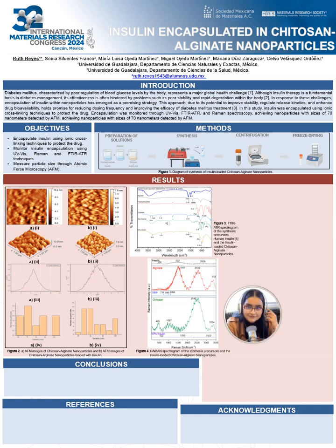We then turn to the Raman technique, where we also analyze the precursors. The image shows the signals corresponding to each one. In this case, the nanoparticles being organic do not present well-defined signals, but if we zoom in, we see three attenuated peaks. The first peak corresponds to the presence of TPP and the polymers present, which are alginate and chitosan.